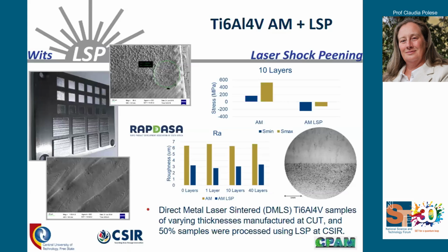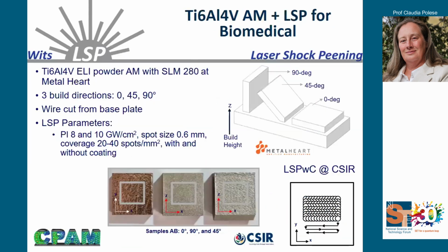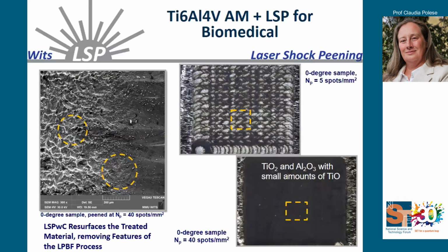So again, here the idea was to come with laser shock peening and to see how we can potentially fix problems that are inherently part of the metal additive manufacturing process. So usually a quite rough surface, adverse residual stresses, possibility of porosity. So we tried laser shock peening in collaboration with colleagues from the Central University of Technology on titanium additive manufacturing. And we use it for both, let's say, aeronautical application, but also on biomedical, because obviously there is a lot of work that is going on there.